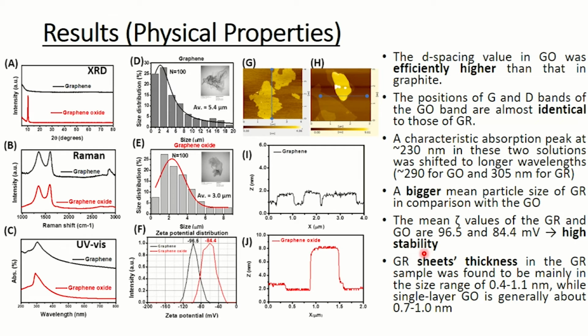In addition, to perform the horizontal dimension observations, atomic force microscopy is regarded as a convenient approach for thickness measurements and layer number counting. By using AFM, we found that the graphene sheet thickness in the graphene sample was mainly in the range of 0.4 up to 1.1 nanometers, while a single layer of graphene oxide is generally about 0.7 up to 1 nanometer.